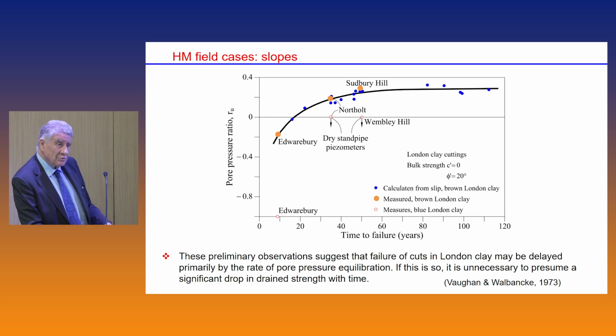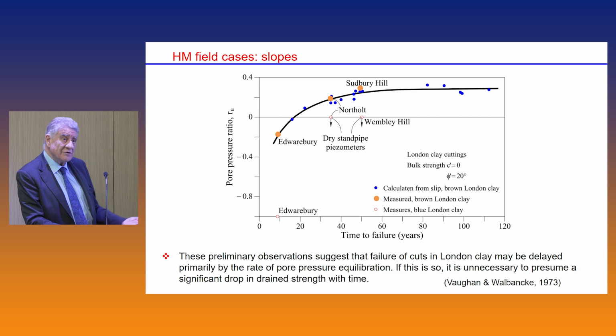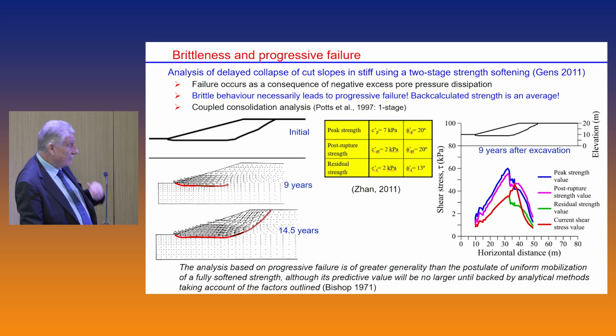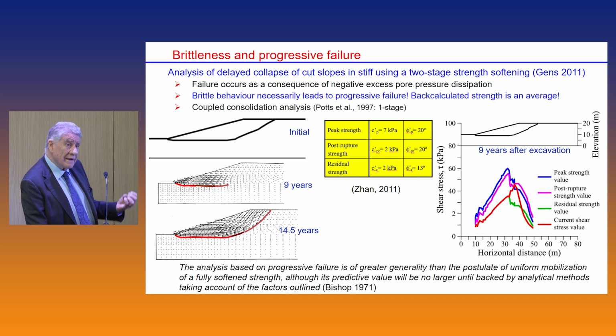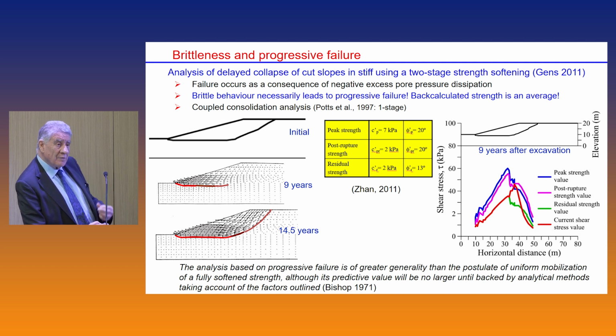So you didn't have to postulate an additional mechanism a bit out of nowhere. The reason why the back analyzed strength was somewhere between peak and residual comes from the realization that brittle behavior leads to progressive failure. In a progressive failure along a landslide, there will be some parts which are residual, some parts which are at peak, sometimes somewhere in the middle. So what you calculate is not the strength of the material, it's an average strength. It's wrong to think of a single strength.